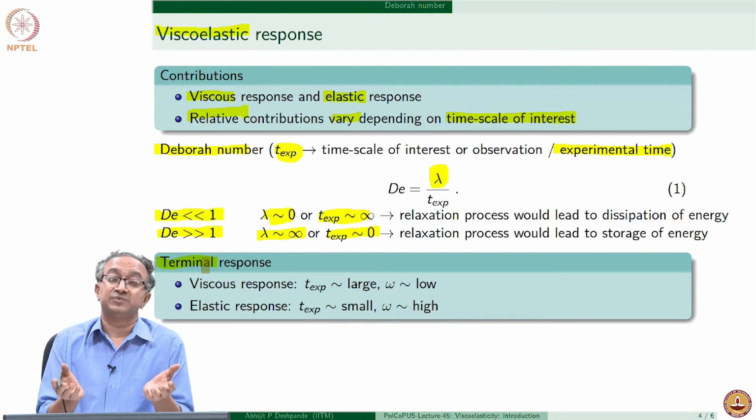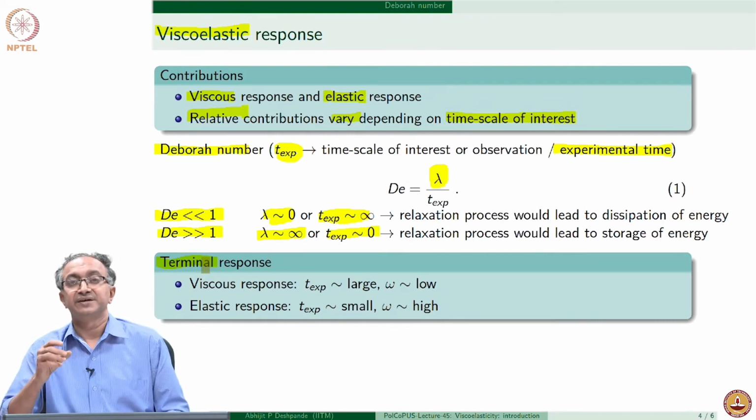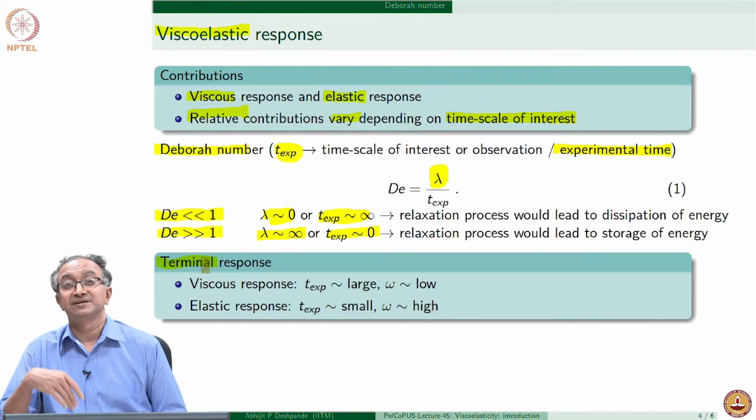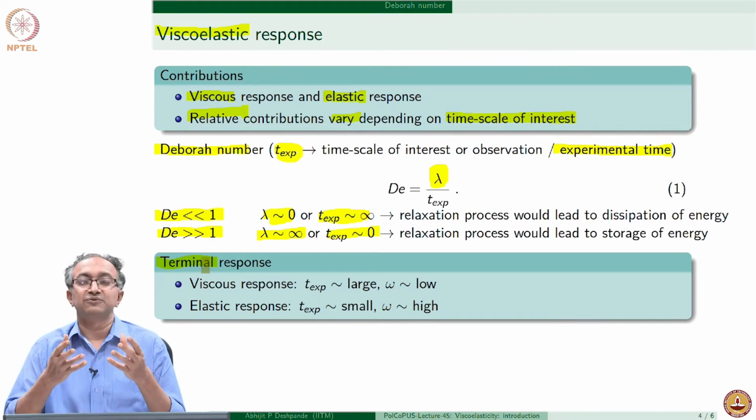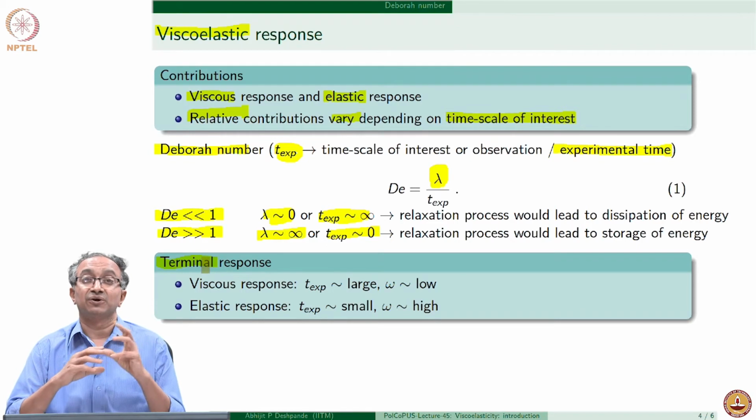We can also think in terms of polymeric solids, that if I do an extremely fast experiment where I apply the load, the polymeric molecules do not get a chance for untwisting or conformation change or any of the features which are associated with dissipative response.